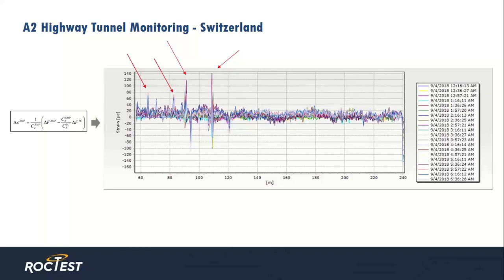Okay, to follow the previous slide, strain variations in the localized section of the tunnel can be seen here in the microstrain versus location plot. Strain peaks here are called out in red, and they correlate to individual cracks in the tunnel lining.